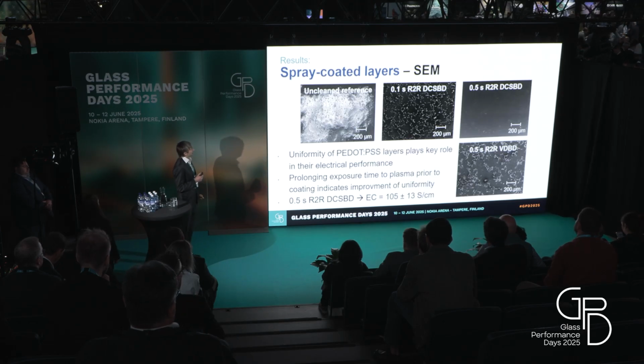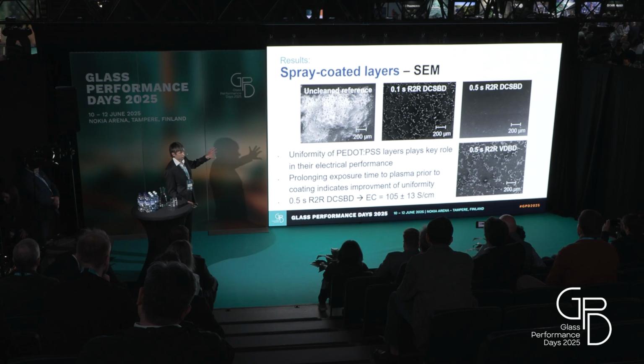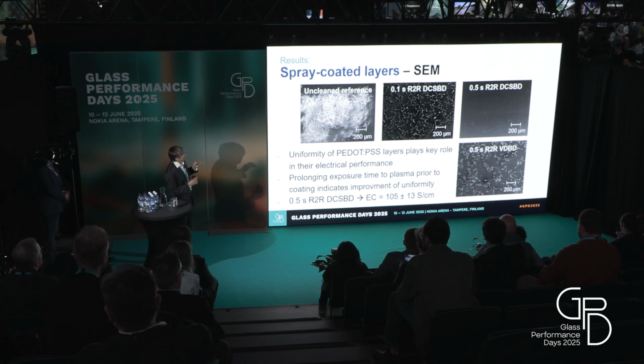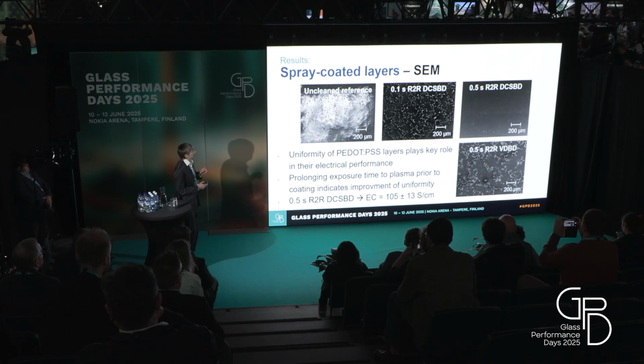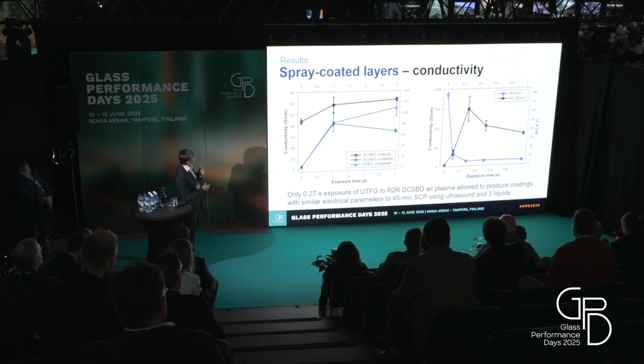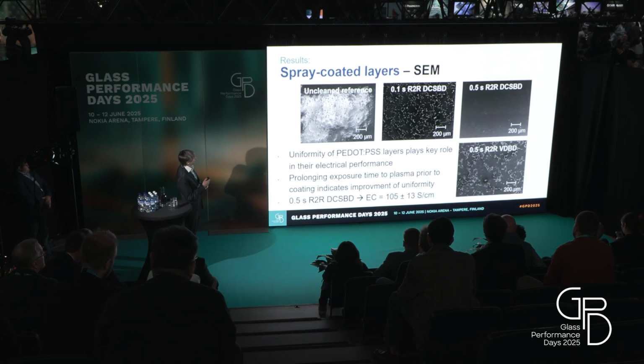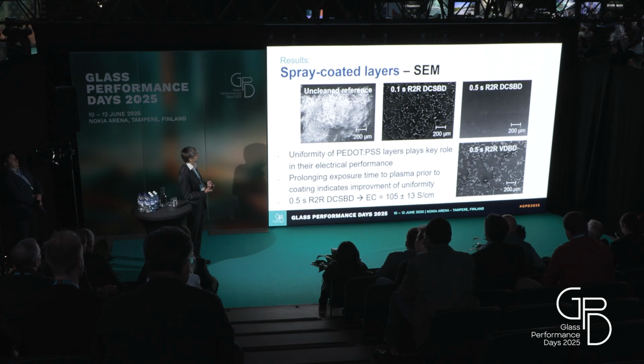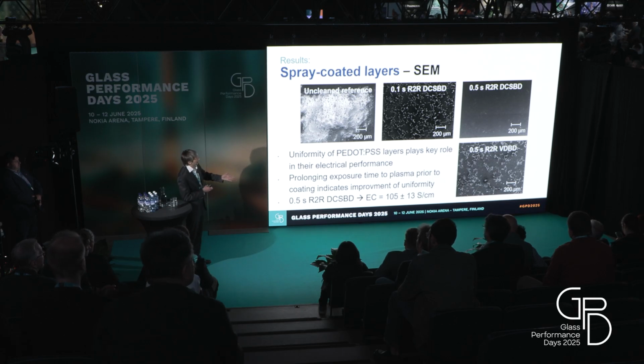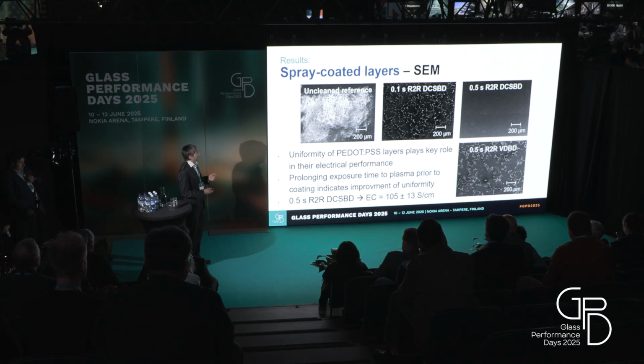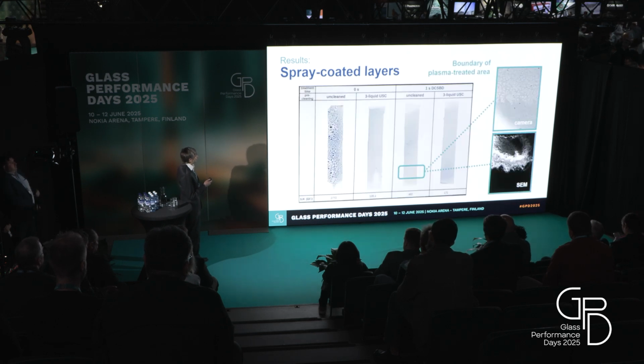This can be seen in these pictures. And we observed that the uncleaned reference has a lot of defects and the coating forms small islands. On the other samples, we also compared with a roll-to-roll DBD, the blue line, and we see that the effect was faster with the DCSBD, and also the conductivity was better for roll-to-roll DCSBD. So it's due to the similar character of the plasma, and the effect of DCSBD, due to the very thin layer, was faster. So after 0.1 second, it looked like the samples of 0.5 seconds for roll-to-roll DBD. And this time was sufficient to prepare a sample with a uniform coating with the DCSBD plasma.